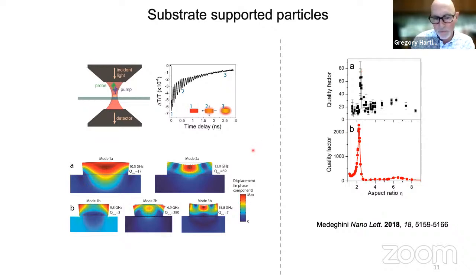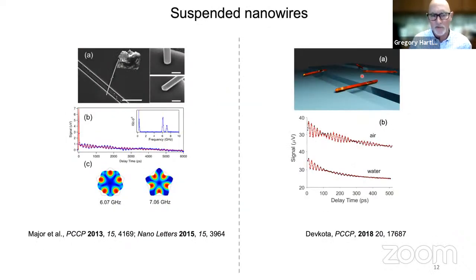For localized plasmon resonances, you have a bit of an analogous effect. You can change shape and make dark modes that don't couple very effectively to light, and they can have narrow resonances. A sort of trivial example of that is a quadrupole mode. And so you can do the same thing with acoustic modes, control radiation damping by controlling their shape. However, for acoustic modes, there's actually a much easier way to do that, and that's simply to get